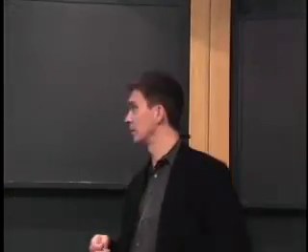So what you can do is literally calculate the Hamiltonian, or in this case the energy, for a lot of these configurations. Let's say there are 20 of these V's you have to determine. Then if you have the energy at 20 different configurations, you could determine the interaction coefficients. Typically, people use very overdetermined sets. So if you want 20 of these, you may do 50 energies and do a kind of least squares fitting, just to make the determination of interactions much more stable. But that's essentially how it's done.